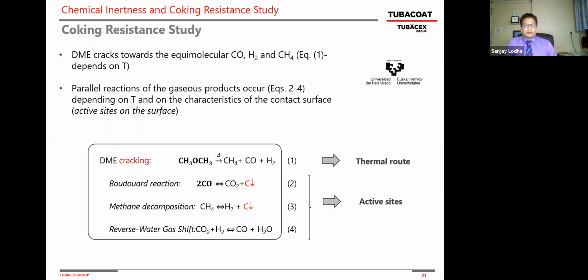So this experiment was done with the European university, where we took the chemical compound dimethyl ether and cracked it. If we crack it properly, it's equimolar cracking into carbon monoxide, hydrogen, and methane, and it won't generate any coke. That's a thermal route. But it doesn't happen in real life. You have many side reactions, the Boudouard reaction that breaks down the carbon monoxide to CO2 and carbon, methane decomposition, again into hydrogen and carbon, and this carbon is what you don't want in the furnace tubes.